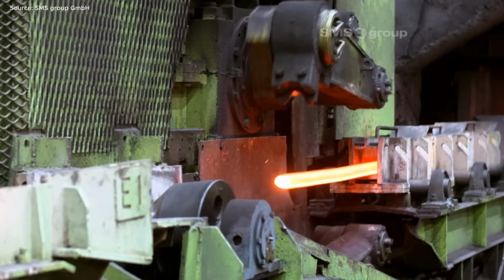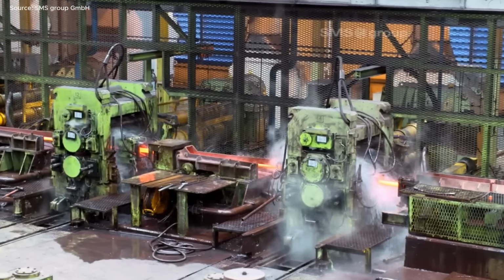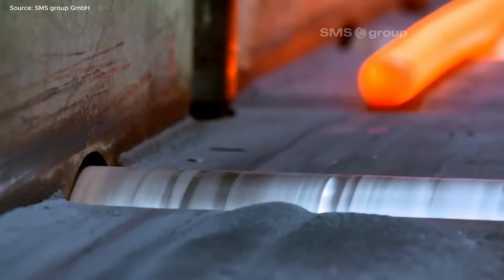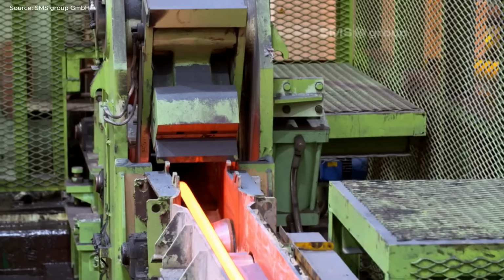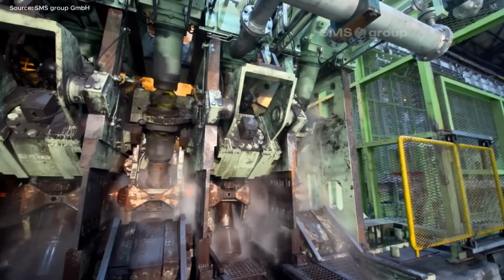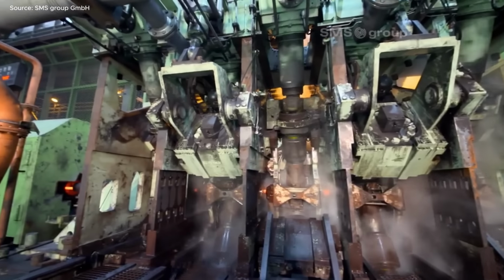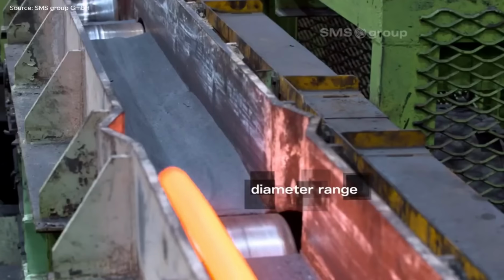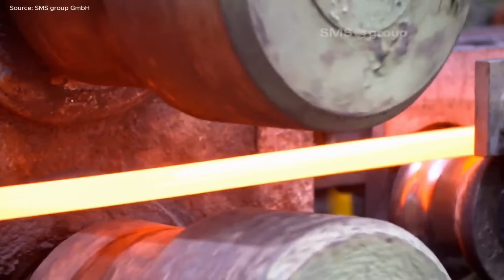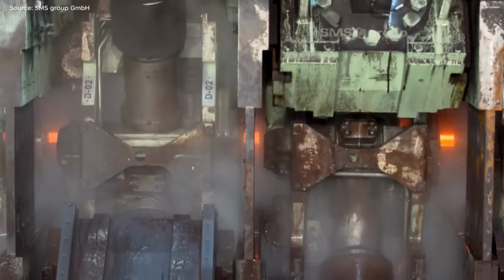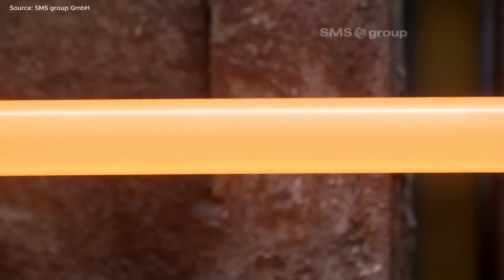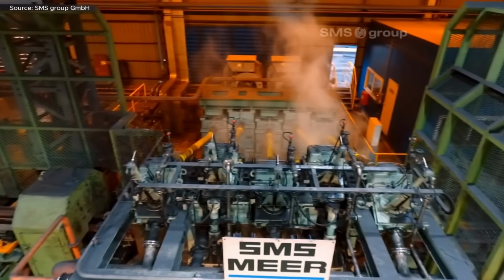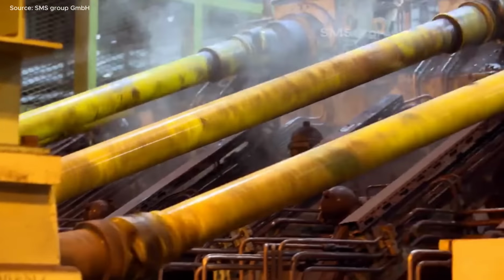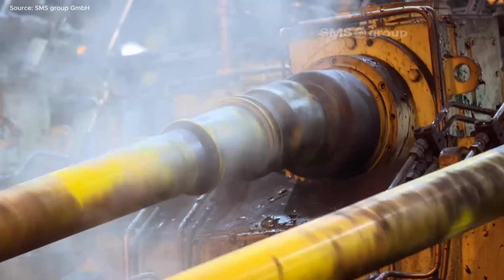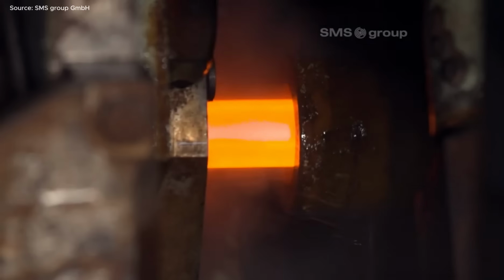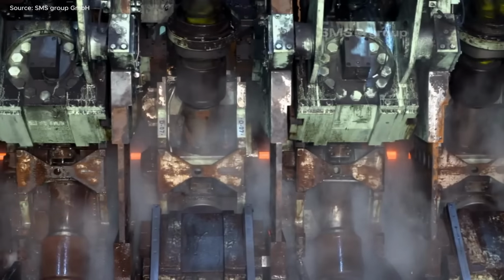Each of the 3 rolls in the PSM completely encloses the material, producing a perfect round cross-section. The PSM features hydraulic roll gap adjustment under load, enabling diameter corrections within milliseconds during operation. Each stand is individually driven through high-torque gearboxes, designed and manufactured by SMS Group. This system ensures stable torque transmission, smooth material flow, and dimensional tolerances up to 10 times more accurate than DIN standards.